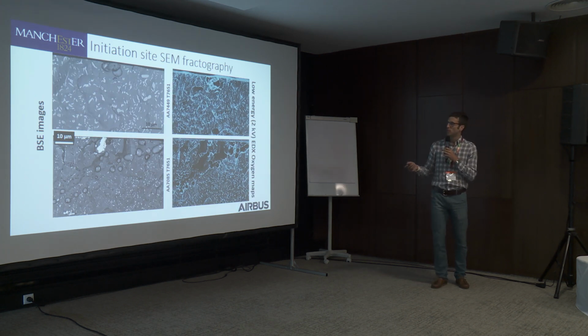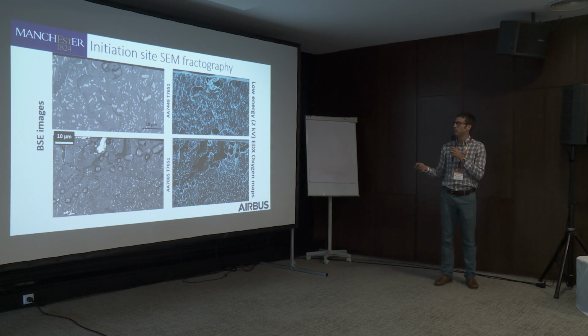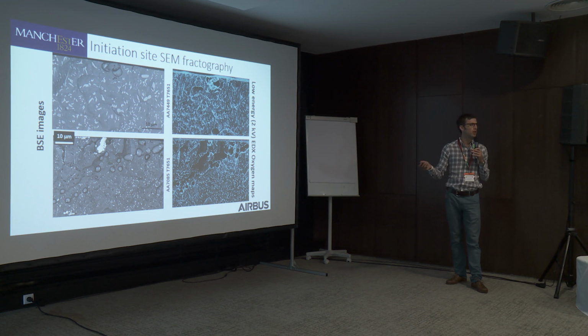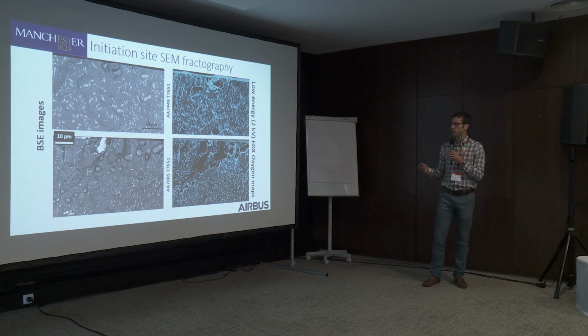But with that knowledge now, we can look a bit closer. What we've been doing is very low energy EDX mapping of the surface. This is something that you could do and easily miss if you weren't confident that you were looking in the right place. But using 2 kV mapping of the surface, we can now see these crack arrest markings around that initiation site. So it gives us even further confidence that we found exactly the right place. But we can also see some elevated oxidation at some locations, which coincide directly with those initiation sites.